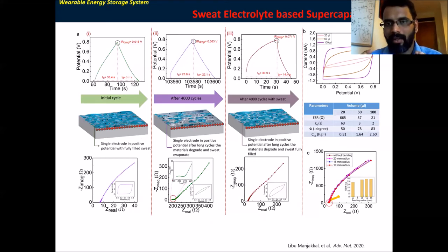Here the question will come: when we are using human sweat, it can evaporate very easily, as we notice when we run, our sweat gets wet, and then what happens after evaporation? To solve that issue, I did the following. You can see the initial cycle here. I dropped the sweat on the electrode and did the analysis. You can see the resistance is less than 10 ohm, and a perfect charging and discharging, with almost 33 seconds charging time and 31 seconds discharging time.